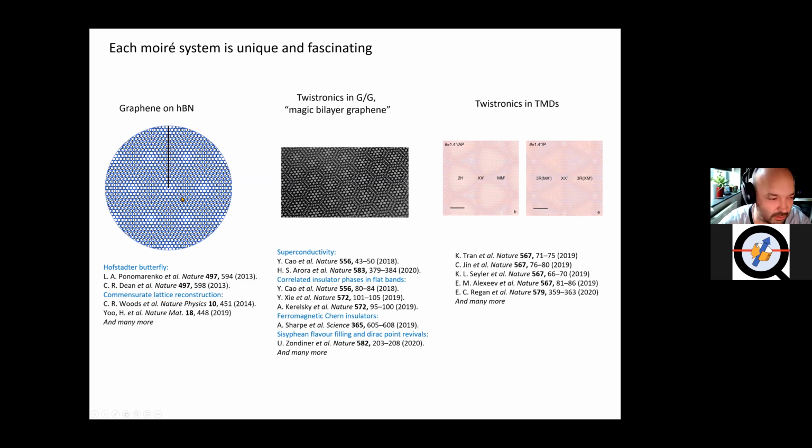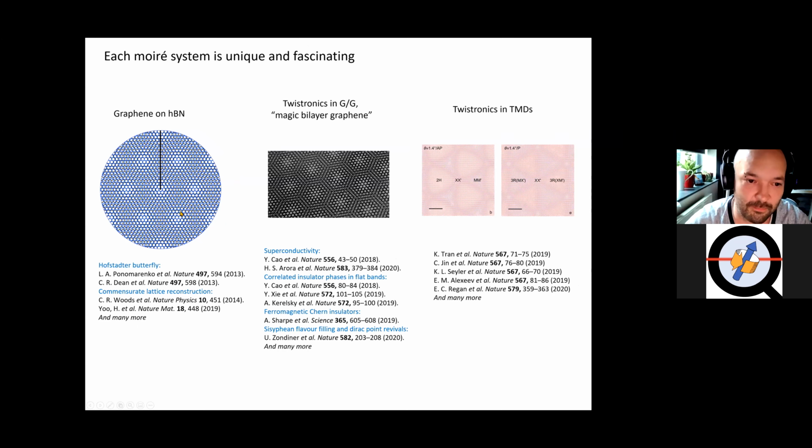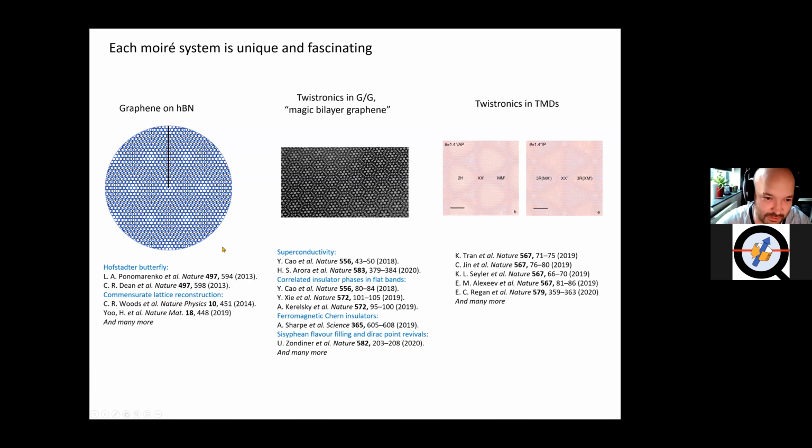so-called Moiré pattern. So the lattice constant of graphene is 1.8% different from boron nitride, and it's also hexagonal. So when you put them on top of each other, you can see there is the superlattice appearing, and if you then start rotating them relative to each other, you can control the period of the superlattice. And that is what Twistronics is about.